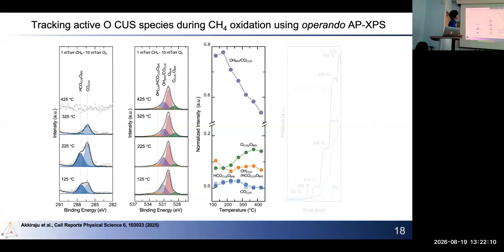And this is the carbon 1s spectrum. What you can see is that at 125 degrees, you form carbon-containing species, which means that methane has been broken on the surface, activated, and you have reaction intermediates corresponding to what happens when methane reacts with iridium oxide. So you have two different intermediates here.